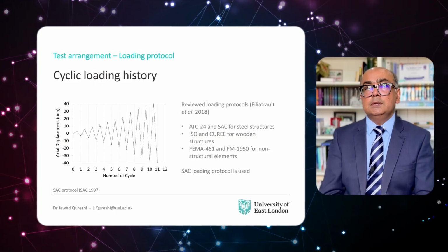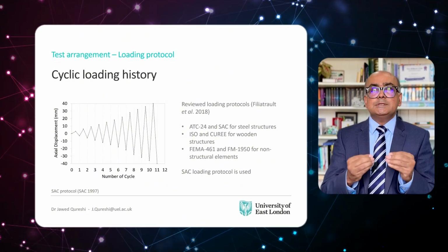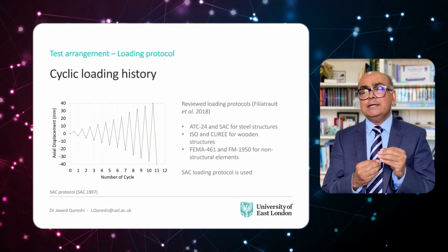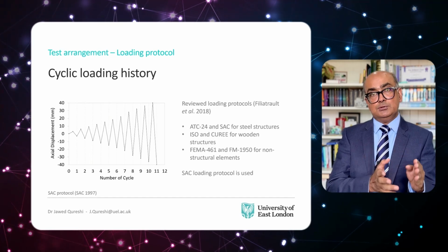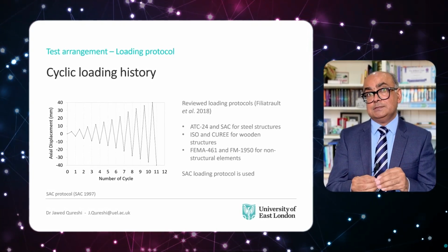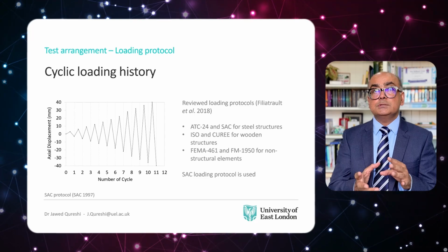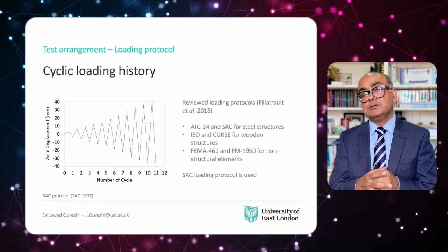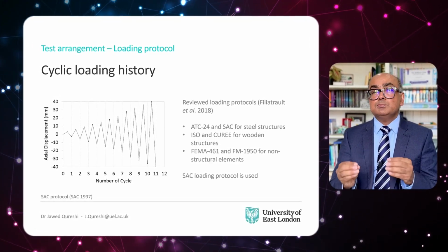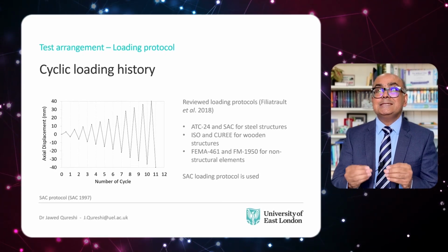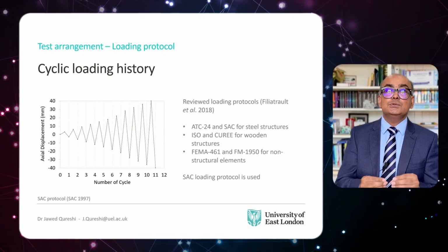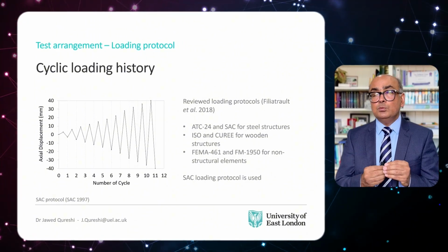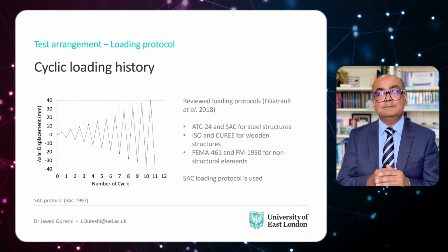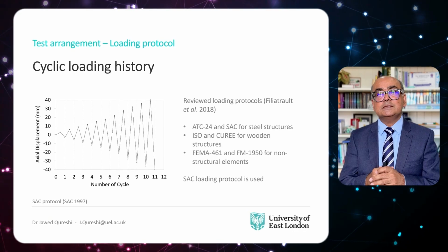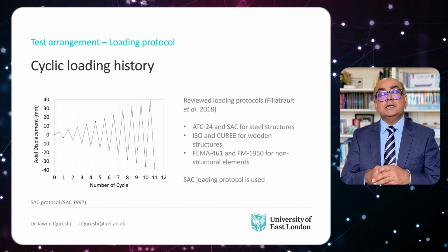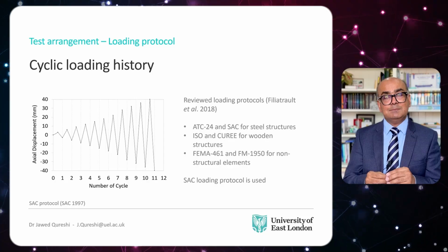Loading protocol. Now this is very interesting. In the absence of ductility, finding a suitable loading protocol was a bit of a challenge for us. We reviewed loading protocols for steel, timber, and non-structural elements. As most protocols were based on steel yielding, we decided to use SAC loading protocol, which is based on displacement. And here you can see number of cycles versus axial displacement. That is how we applied loading to the specimen.